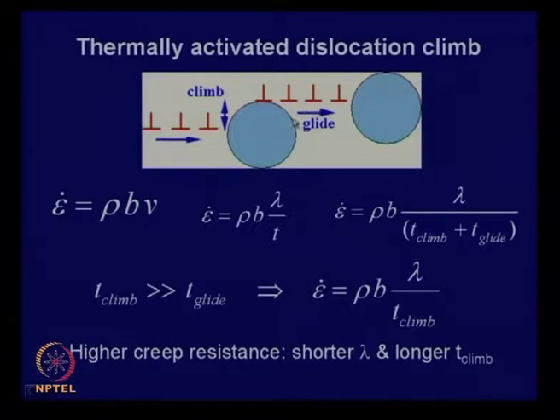So, you have precipitates, and lambda is the distance between the two. This is the creep rate equation, with dislocation density, Burgers vector, and velocity, and the key thing is you can assume that the time to climb is the total time. This time has two components. These are the layer of dislocation pile up which has formed against a particle. Now, the dislocation has to climb to overcome this, and this makes the process very difficult.